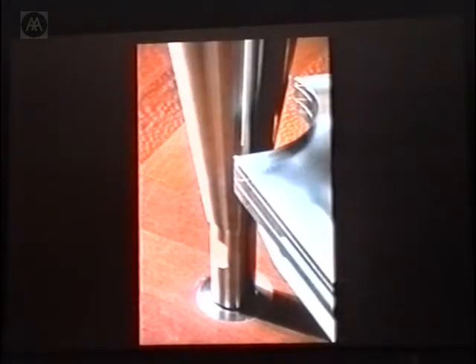But well, I'm talking about principally glass tonight, and this is the makeup of the tread. You can see, we didn't even, I think Jamie just specified that. We didn't even look at this in truth. But you can see it's 3 pieces of laminated glass, laminated with a very fine laminating material with a sandblast on the top. And that's the support condition underneath. We had 2 little spars onto the basket.